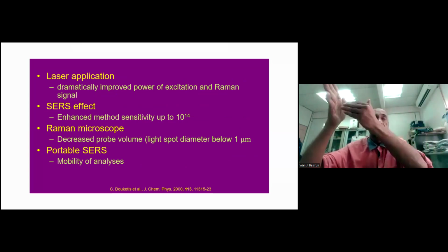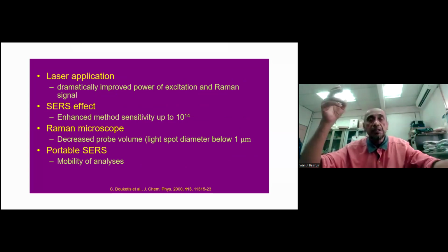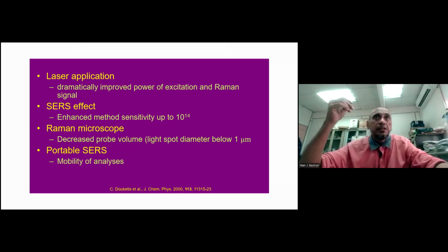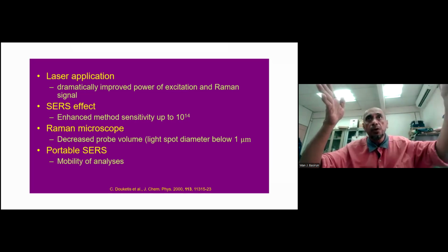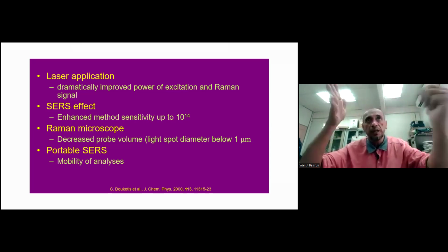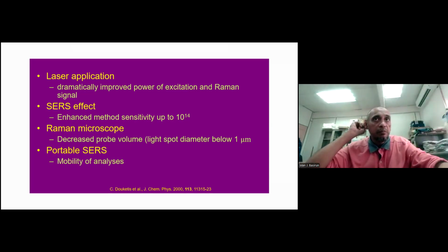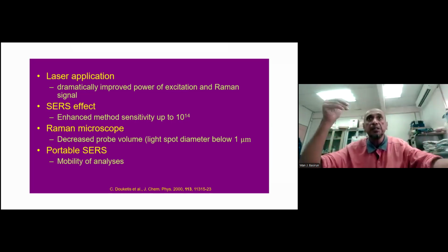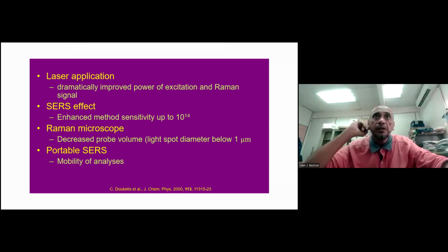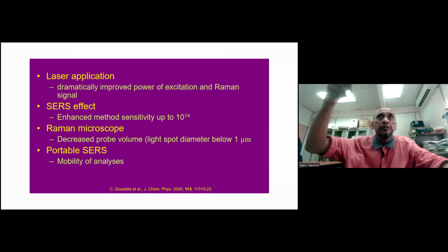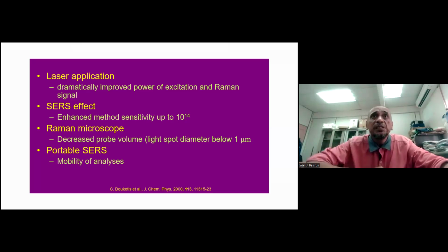So when this laser is scattered, you get a very large intensity, which can be used to enhance this technique. For example, when they use a laser as the source of excitation, or the source of the incident light, Raman spectroscopy became even more useful, because the incident light becomes high intensity compared to the previous radiation without the use of lasers. And in the case of surface enhanced, this method can enhance the sensitivity up to 10 power 14. So it is a very, very sensitive technique.